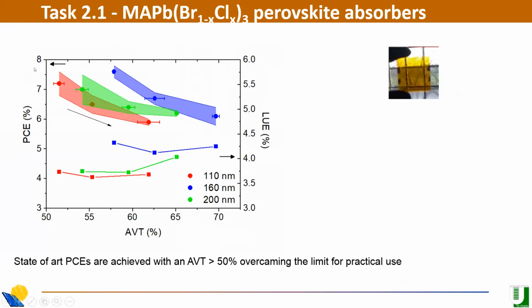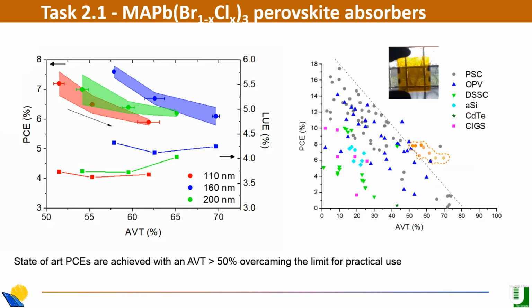This is the power conversion efficiency and, as usual, the transparency, the AVT. Look at the top curves here: you see that you can get something more than 50% transparency with an efficiency between 6 and 8%. So it's quite interesting to have a solid state technology, not a molecular technology, that could achieve more than 50% transparency. And this is the plot summarizing all the results published to date in literature, showing efficiency and transparency. The results we recently obtained were in the range here, so quite overcoming the results published in literature so far. So it's a new strategy to get good transparency and at the same time good performance.